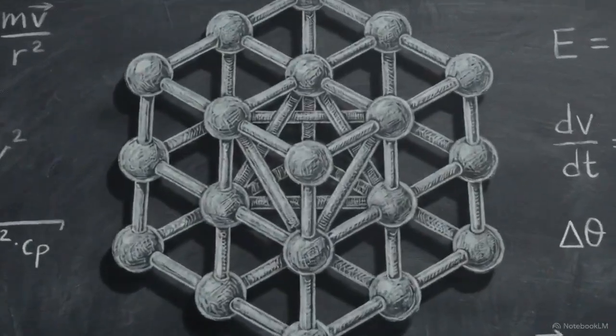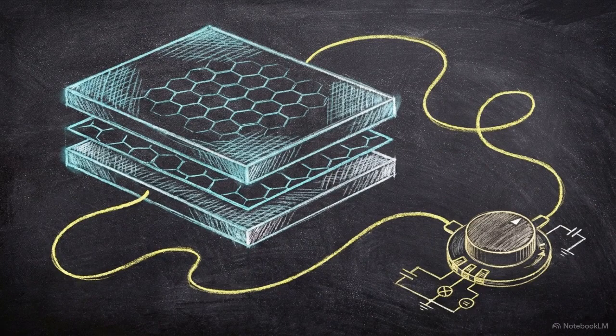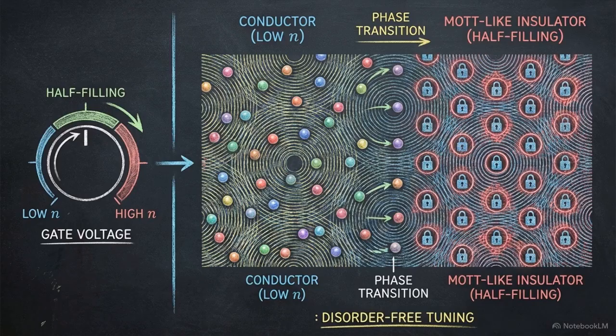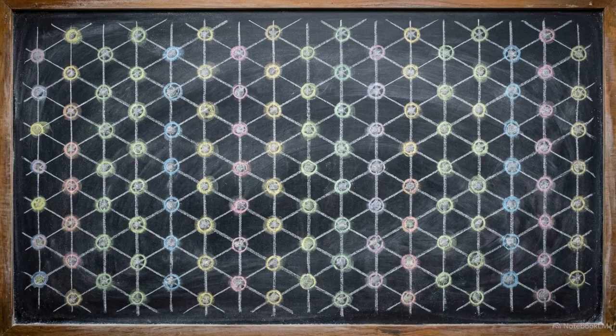Traditional correlated materials are often locked into complex chemical structures that are difficult to change once the crystal is grown. Magic angle graphene is different. Its electronic states are continuously adjustable using a simple gate voltage. Turning an electrical dial adds or removes electrons, pushing the material in and out of the flat band insulating phase without adding disorder. Twisted bilayer graphene functions as a dynamic quantum sandbox, providing a level of control that static chemical structures cannot match.